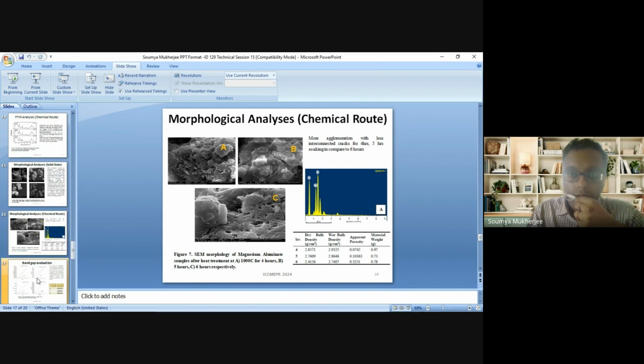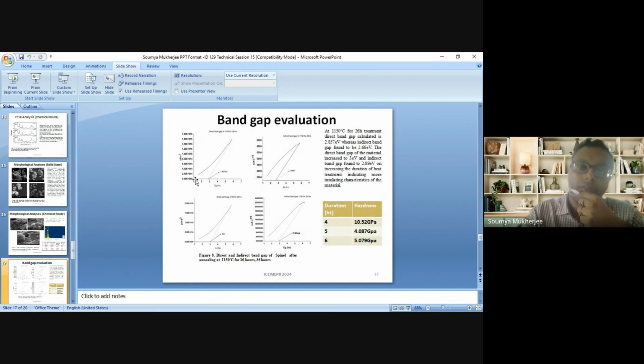Now moving to band gap analysis, we have calculated the band gap by utilizing the Tauc relation, and the band gap is in the range from 2.85 to 3 electron volts, which is quite close to semiconductor insulating nature. We have also measured the hardness value of the chemical route processed spinel sample, and the hardness values for 4 hours, 5 hours, 6 hours are correspondingly 10.52 gigapascal, 4.087 gigapascal, and 5.079 gigapascal.